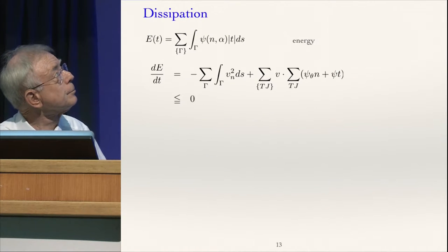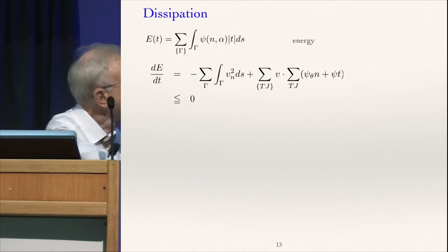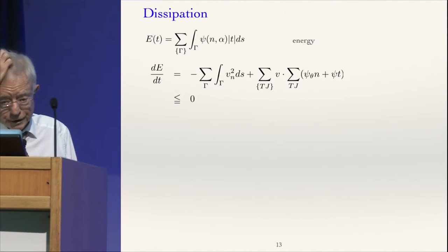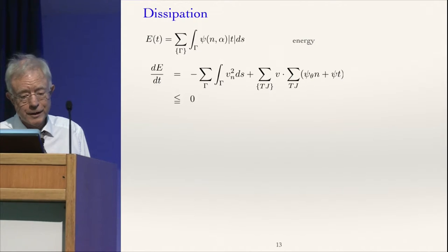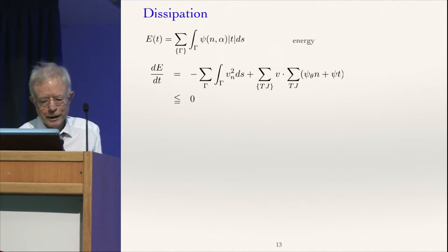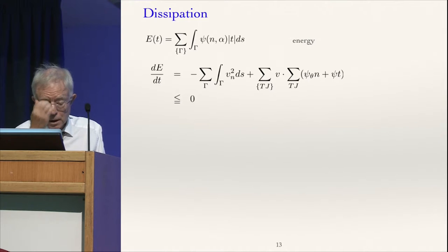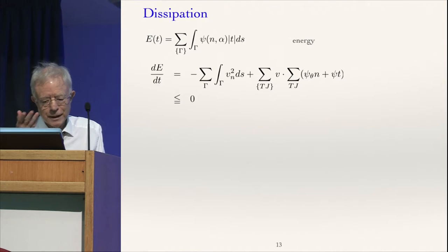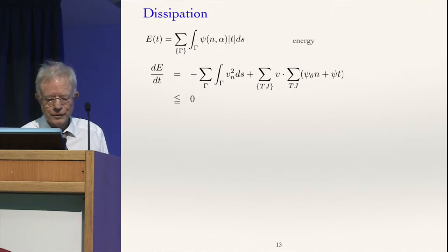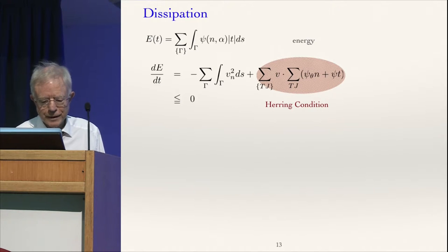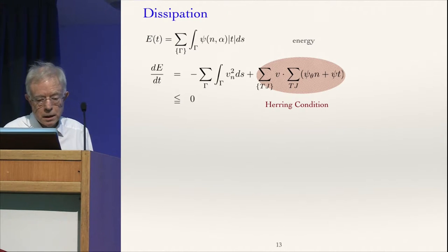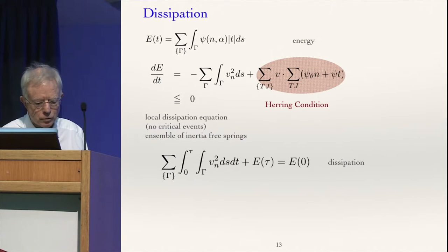Now, there's dissipation in this system, and that's very important. So the energy is written there. It's just the sum of the energies over the curves. This is about the only calculation we're doing this afternoon. The rate of change of energy is minus the sum of the integral of the Vn squareds plus V dot, these sums over triple junctions of those forces, but by the Herring condition, that vanishes. And so the system is dissipative. And that's a local dissipation equation.